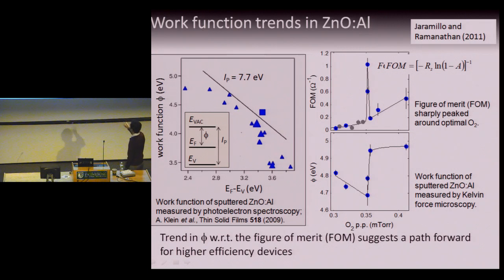However, right there at optimum oxygen content, it turns out that the work function has some pretty funny non-monotonic behavior. It varies sharply and steeply over several hundred millielectron volts. And so while this is good for transparency and conductivity, this is not good for predicting the efficiency of your resulting device. This sort of thing has been seen before, as it turns out.